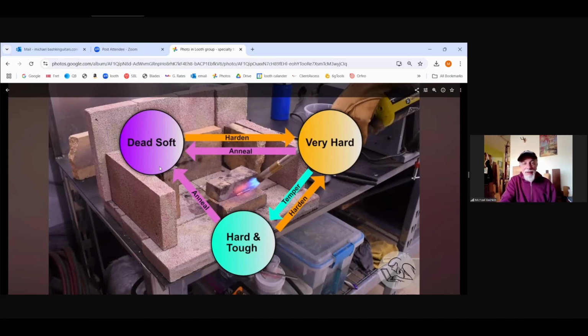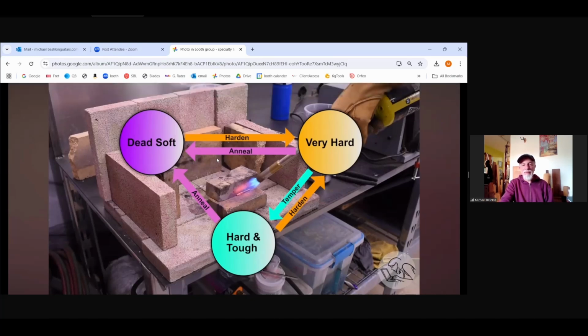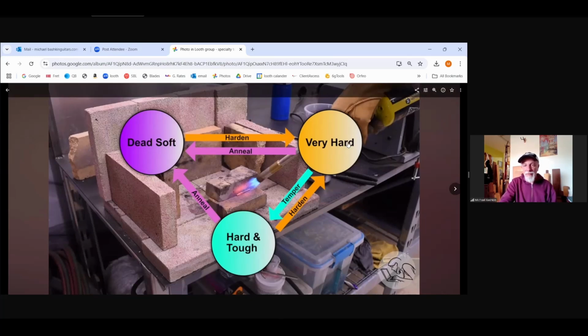All right. So when I bought the O1 steel, it comes in an annealed state, or in this diagram, it's called a dead soft state. It's about a Rockwell hardness of 35, and it's very easy to work with files, hacksaw, grinders. It's very soft. And then you need to harden it. And so we're going to bring it up to that temperature of 1450 to 1500 degrees, and we'll do that with a propane torch.